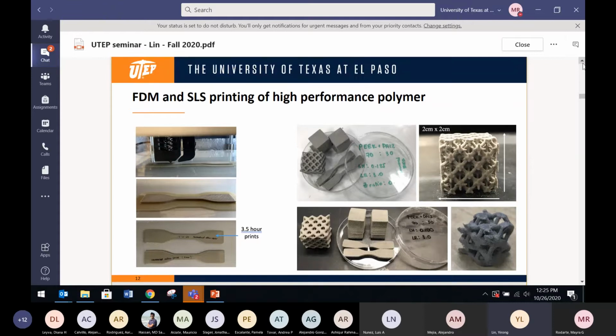The other thing we've been working on is printing functional polymers, especially high temperature polymers, because polymer is great, right? But the problem is polymer usually melts at less than 300 degrees C. That really limits a lot of applications, especially in high temperature domains. So what we're pioneering is using two different 3D printing technologies, namely FDM and selective sintering, to print a polymer called polyether ether ketone, or PEEK. This PEEK has a melting temperature above 420 degrees C. That opens up a lot of opportunity to use this polymer for high temperature applications, such as hypersonics, which require materials for high temperature and high velocity applications.